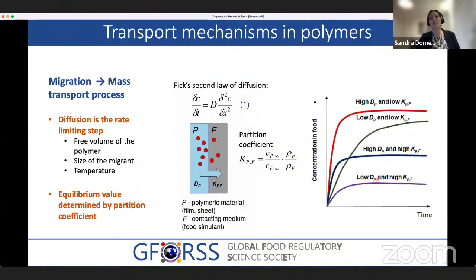You have different situations then to manage here. The first situation, which is the best situation for any food safety manager, is that you have a very slow process, so a low diffusion coefficient and a high partitioning. So it is slow and it doesn't go very thoroughly to the food. So there you have little contamination. Then you can have a quick process, but still not a very high affinity of the contaminant to the food, still an intermediate situation here. And then this shows you that when the partitioning coefficient is low, which means that your contaminant is liking the food, you always have a problem in managing your safety. And you have this problem when you have slow kinetics. And of course, the most concerning situation is going to be a very fast process and a high solubility of the contaminant in the food.